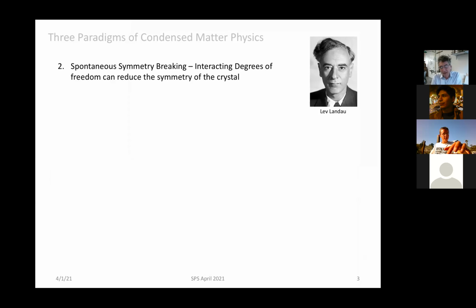Okay, the second paradigm is called spontaneous symmetry breaking. So now imagine you have a lattice, and the lattice is fixed; it's not changing, and it defines the space. Well, what if you have degrees of freedom that are interacting? For instance, conduction electrons can interact with lattice vibrations, or if the valence electrons are not conducting, but they're localized on the atomic sites, then they'll become magnetic. They'll have a spin or local magnetic moment on the atomic site, and these spins can interact via various types of interactions, usually called exchange interactions. And when they interact, they can do this in a way that breaks the symmetry. The original symmetry of the crystal lattice can be broken.